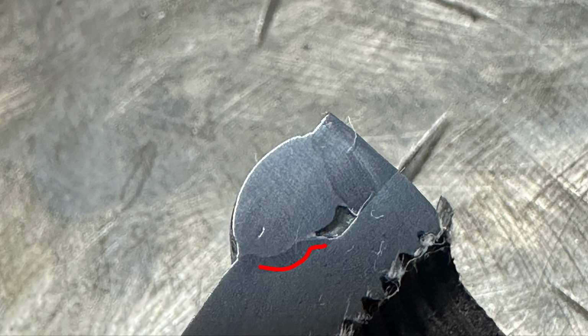Anytime you weld two thicknesses, one thick, one thinner, the weld is always going to favor and melt into the thinner material better. So you really got to watch stuff like this with cold settings because you're going to get a real bad lack of fusion on one of the two. Now, realistically, would this fail? In most circumstances, probably not, but there's a couple things you got to remember here.